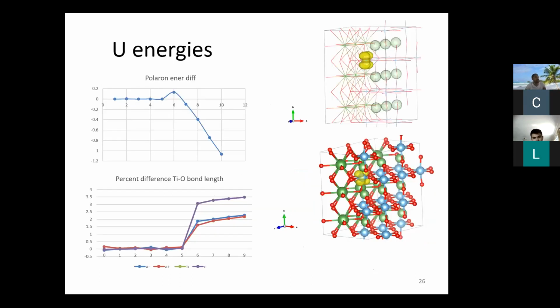As I mentioned, I was tuning this U parameter, and we didn't have polaron formation until, when we reran it and changed it up a little bit, a value of 3.4. But just for the sake of this, we actually have a linear dependency on localization. Remember, this is localized minus delocalized. The more negative the value, the more stable the localized state is.